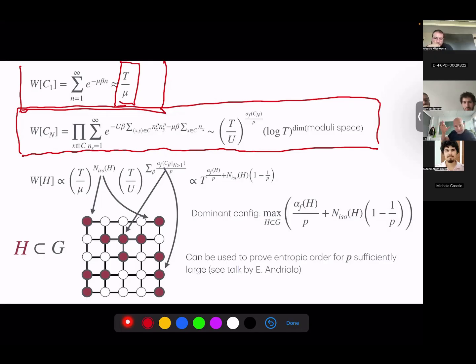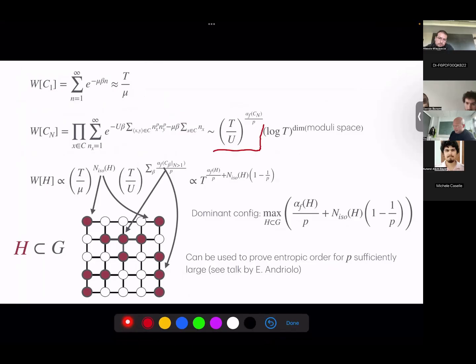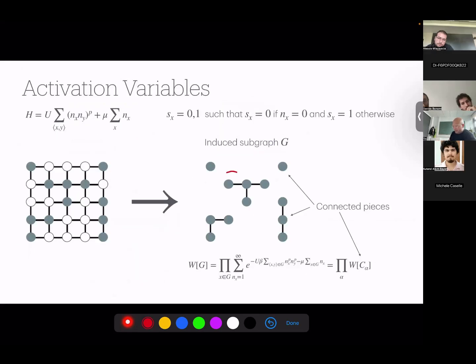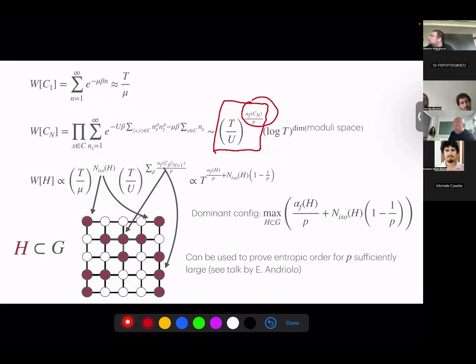And the most important result of that paper is that all these weights of the connected graphs, which have number of nodes larger than 1, scale like this with temperature, where the exponent here is the size of the maximum fractional independent set. In other words, all these connected graphs, which you're supposed to sum over in the partition function, their weight is completely dictated at high temperature by the size of the maximum fractional independent set.